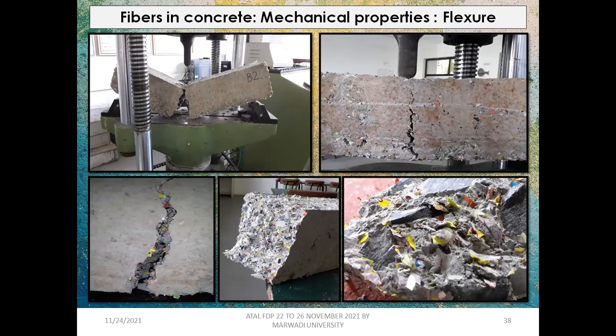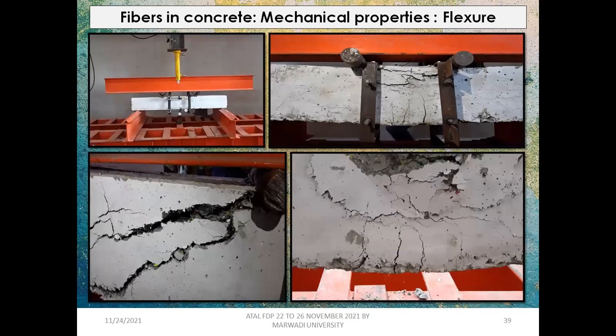I'm not claiming that this is the only thing that we have innovatively done, but it's always good to share the information with each other, at least through publications also. This is the image where we have added fibers in the reinforced concrete beams. As you can see, it's a loading frame, and here we noticed that it contributed a little, up to an extent, within 10% of the change in the typical behavior of the beam.